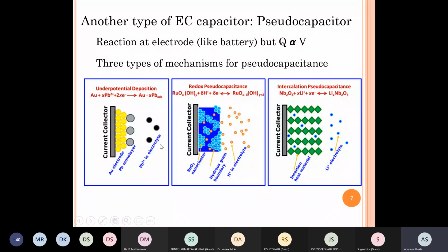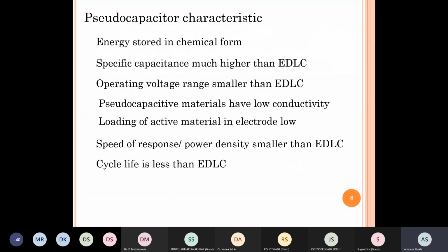So there are three types of mechanism: underpotential deposition, redox pseudocapacitance, and intercalation pseudocapacitance. The more commonly investigated electrodes are for redox pseudocapacitance and intercalation pseudocapacitance. Essentially, the amount of charge stored in a pseudocapacitive mechanism is much higher than in electric double layer capacitance. If we look at pseudocapacitor characteristics, the energy stored in chemical form, the specific capacitance, is much higher than EDLC. Some estimates say that for every surface active entity, an EDLC stores about 0.5 electron, while a pseudocapacitive electrode will store about 2.5 electrons of charge. Therefore, the specific capacitance of the pseudocapacitive electrode is much higher than EDLC.